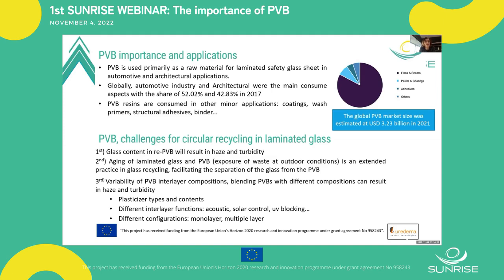Then a second challenge is related to the recycling process itself. Of course, the recyclers right now look to obtain the glass, which is the one that has value. So their aim is to separate the glass from the PVB as well as possible, and for this, laminated glass waste is stored at outdoor conditions. This involves exposure to different ultraviolet conditions, changes of temperature, and humidity, which provokes degradation of the polymer, which makes the later separation from the glass easier. So we have this other challenge: we are degrading the PVB because it's not the focus right now.